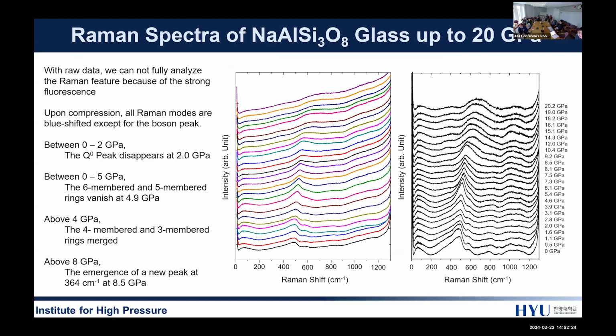In the 800 to 1200 inverse centimeter range, there is the Q mode represented, and at 900 inverse centimeter, the Q0 mode decreases with the pressure and then disappears at 2.0 gigapascal. This means the disappearance of the individual silicate units within the glass.